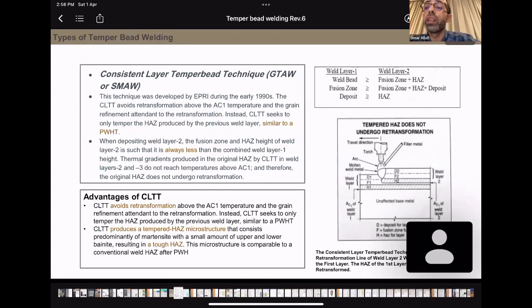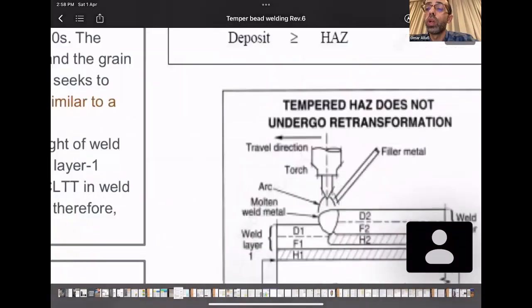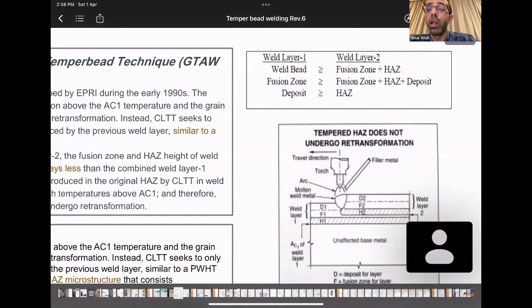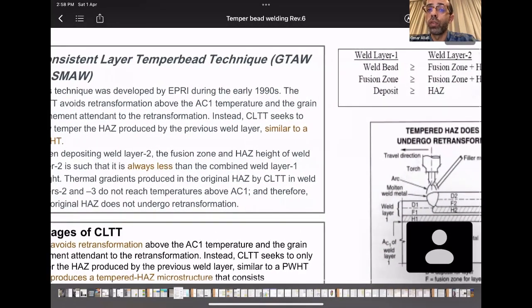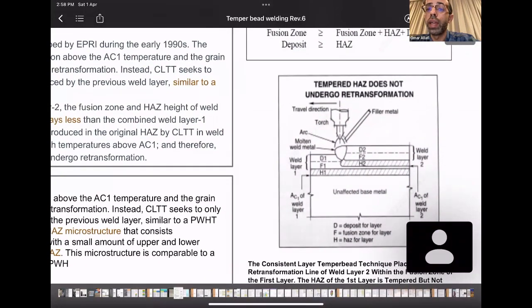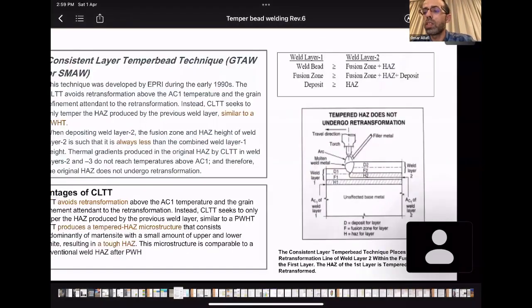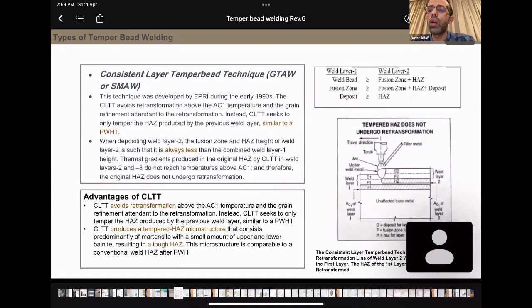when depositing the second weld layer, the fusion zone and height of weld layer 2 is such that it is always less than the combined weld layer. So this is the weld bead, the weld layer 2 fusion zone, and the height of weld layer 2 is always less than the combined weld layer. So this is an overlapping. This is nothing but overlapping. So this is how they control the tempering effect and the mechanical properties of the base metal by overlapping using, as I said, GTAW or SMAW.